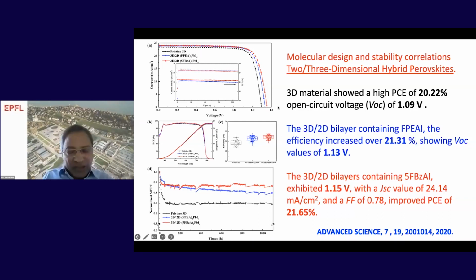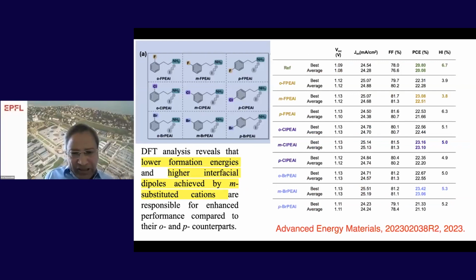The efficiency increase is significant, but however, the more significant data is the stability. The black line is the reference sample. The stability is decreasing, with more than a 30% decrease up to 1,000 hours, compared to the pentafluorobenzylamine containing two-dimensional perovskite. It remains intact up to 1,000 hours. So this is the beauty of having the interface engineering of the perovskite composition by two-dimensional perovskites. So this is our recent work.